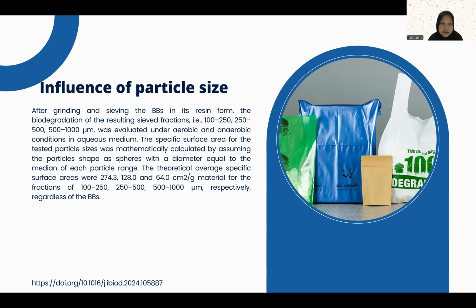Influence of particle size: after grinding and sieving the BBs in their resin form, the biodegradation of the resulting sieve fractions, for example, 100 until 250, then 250 until 500, and then 500 until 1000 micrometers, was evaluated under aerobic and anaerobic conditions in aqueous medium. The specific surface area for the tested particle sizes was mathematically calculated by assuming the particle shape as spheres with a diameter equal to the median of each particle range.